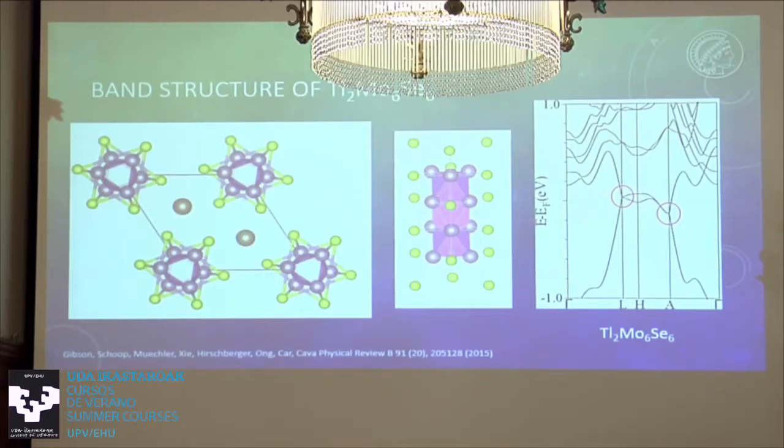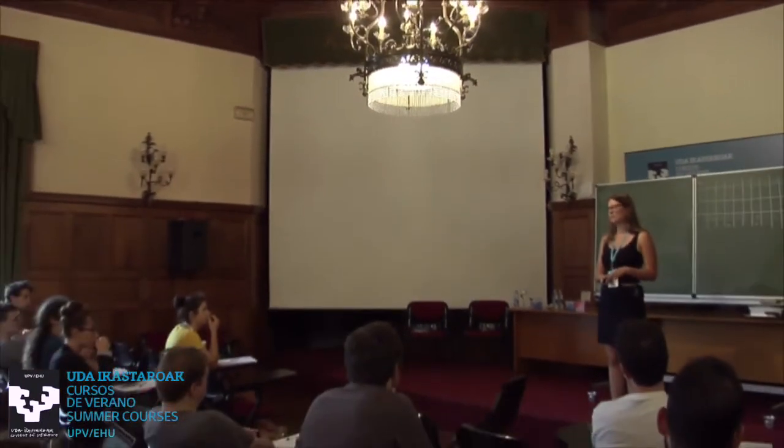And then if you calculate the electronic structure of that, you will see that the non-symmorphic points are relatively clean, relatively close to the Fermi level. Still not perfect, but maybe this is really an idea: delocalizing a half-filled band over a large cluster amount of electrons to get these materials established. And this is the end of my first lecture. And then in the second one, I will give you some more examples of compounds that work.